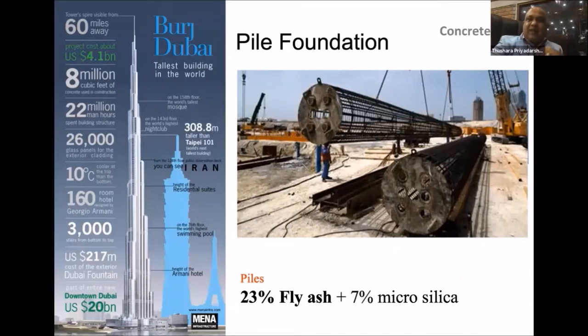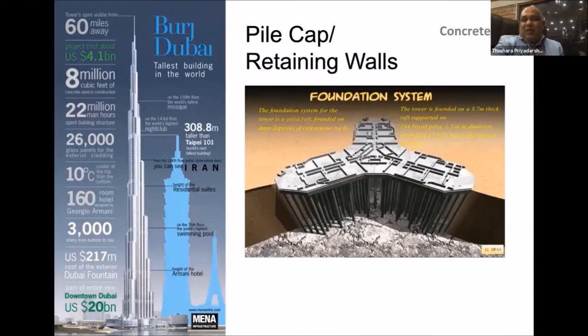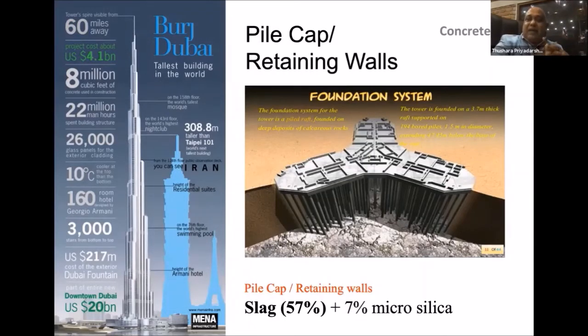So you will see the next example, pile cap or the retaining wall. In the retaining wall, it's a very big structure. Workability is not a critical issue because it's quite huge structures. Then you have a choice to go into either fly ash or the slag. But when you consider these durability concerns, probably fly ash has both these good properties. Second, these are huge structures, then heat of hydration matters. In that case, if you have the option, go into slag-based cement, where you can go for more replacement of cement, and it will give a very slow heat gain, of course, very slow strength gain.